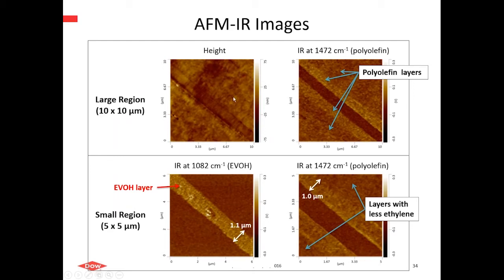We have a height image taken at low magnification of the cross-section that encompasses almost the entire thickness of the film. This is about 10 microns. And then here we're mapping CH2 modes associated with a polyolefin. And we can see a brighter response around the central core, and its intensity then changes as we go further away from that core layer. And at a little higher mag, this is a little bit better resolved. We see what appears to be a higher density of CH2 immediately flanking this core and less so further away.